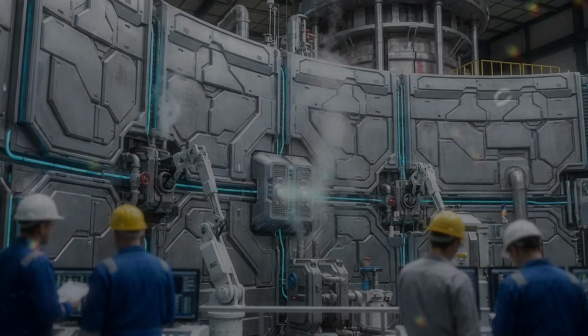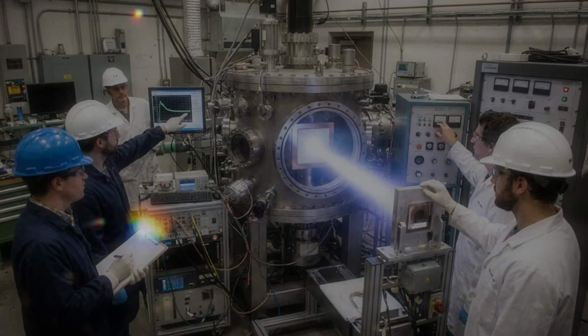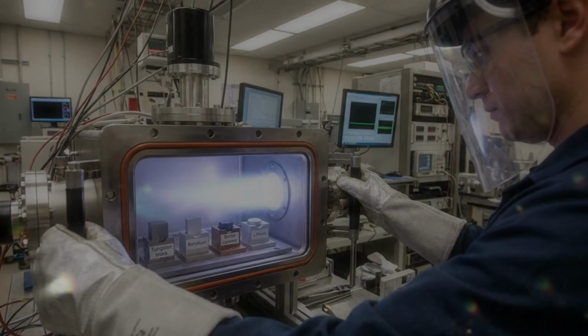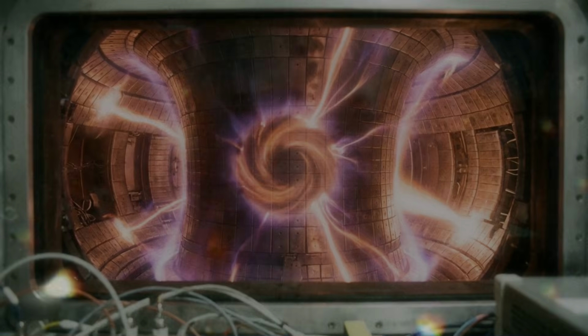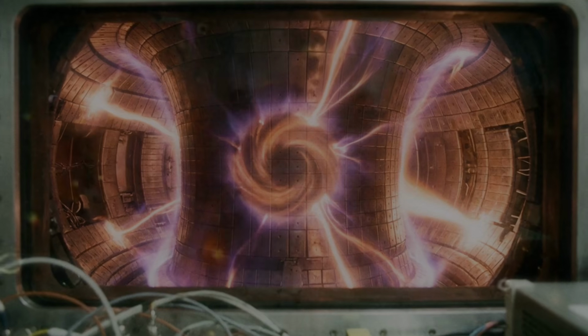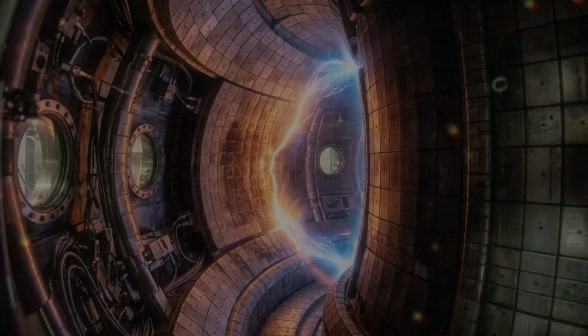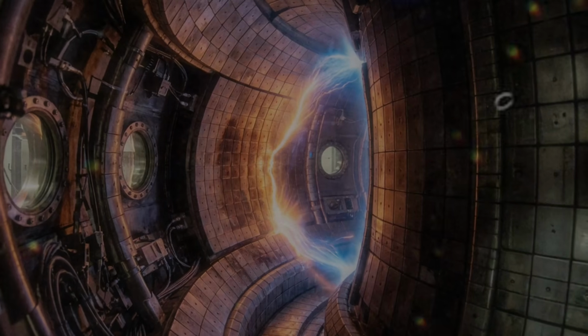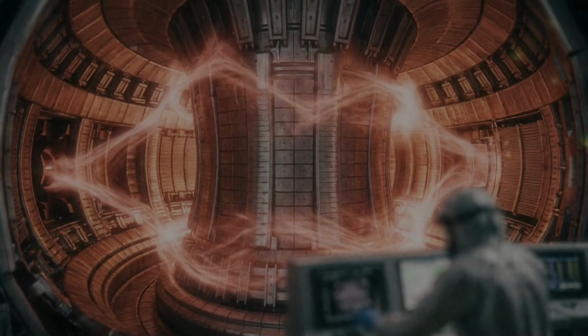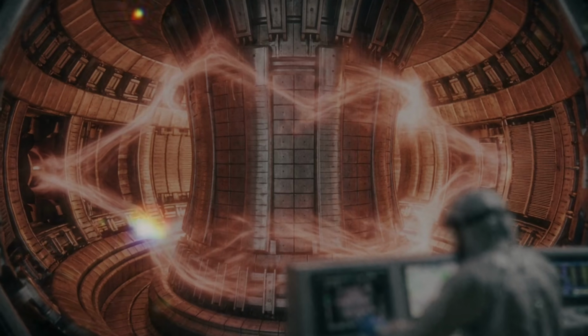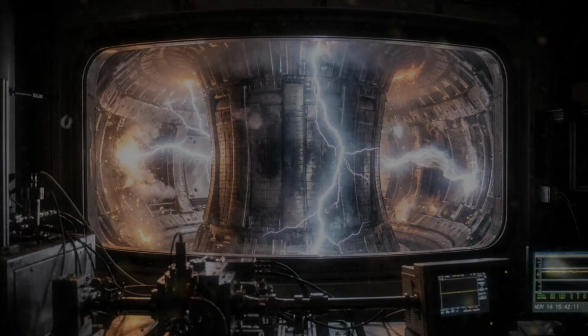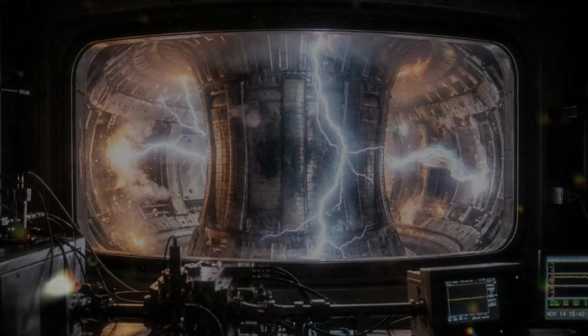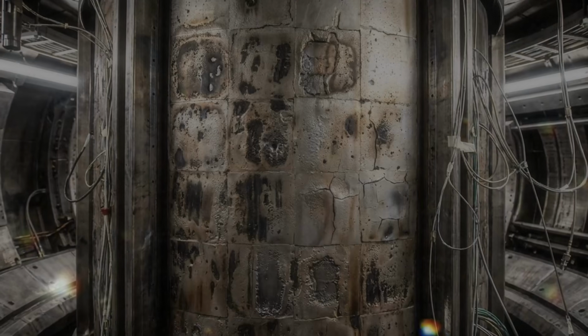So at first glance, tungsten sounds almost ideal. It is hot enough for the job, strong enough to be respected, and stubborn enough to survive particle bombardment better than many competitors. But fusion has a habit of taking promising answers and quietly attaching footnotes. The first problem is that tungsten is a heavy element. That matters because if tungsten atoms enter the plasma, they can radiate energy very efficiently. In simpler terms, tungsten impurities can cool the plasma, and for fusion, cooling the plasma is exactly what you do not want. The plasma must remain incredibly hot for the reaction to continue. Even small amounts of heavy impurity can drain energy from it, so tungsten is excellent as long as it stays where it belongs. If it leaves the wall and joins the plasma, it becomes a problem.